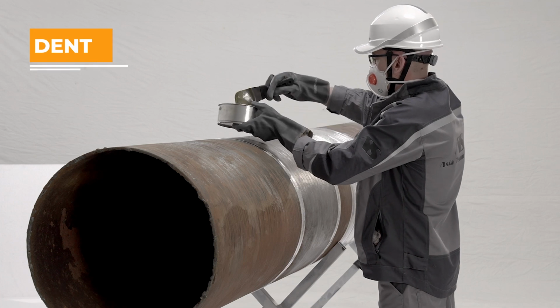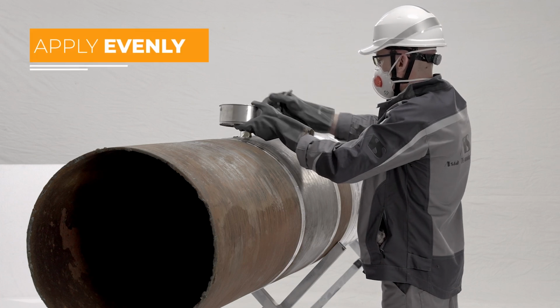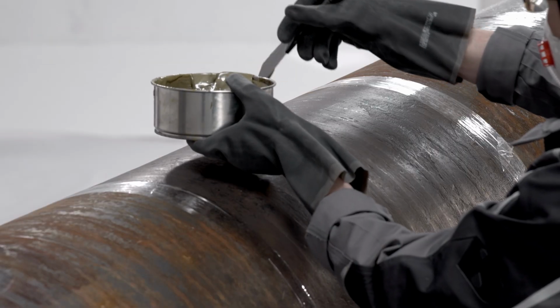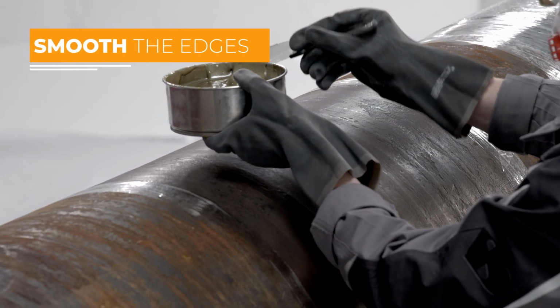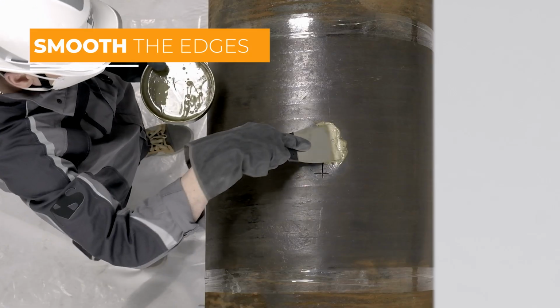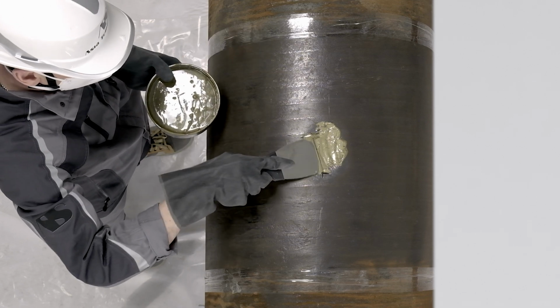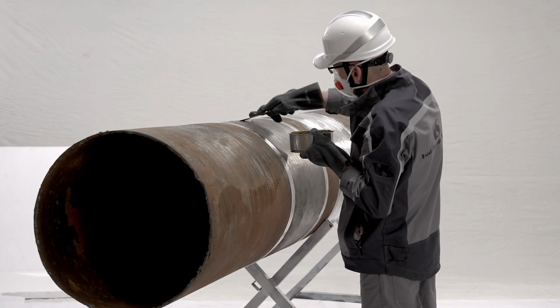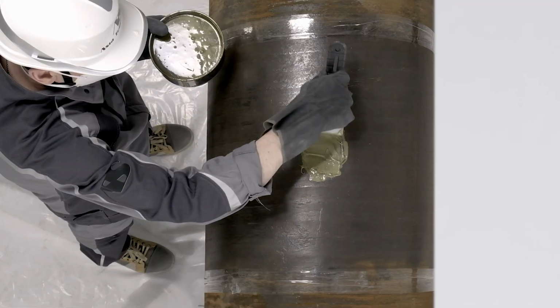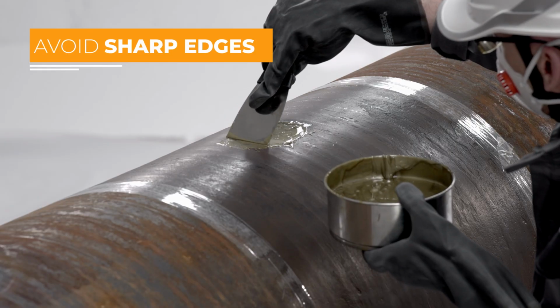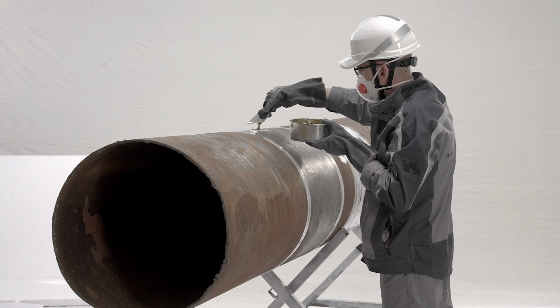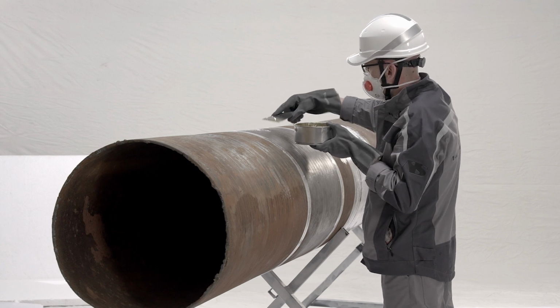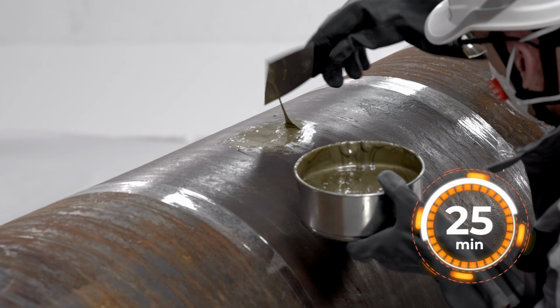Applying the paste to the dent. Use a spatula to apply the paste evenly to all voids. The edges of the defects should be smoothed to create a smooth transition when installing the coupling. Smooth the paste so that it follows the contour of the pipe as well as possible. Avoid forming sharp edges. Wait until the paste has hardened, about 20 to 25 minutes.